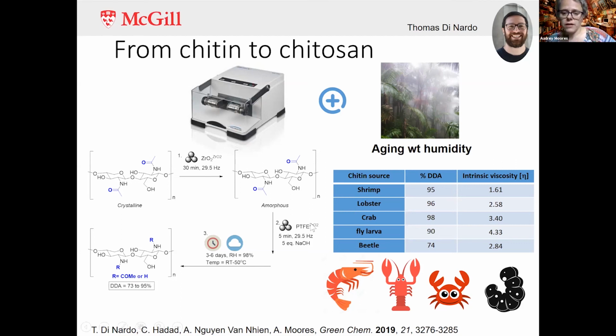Something else that we realize as we do this is that we also make chitosans that have much longer polymeric chains. So we're preserving the structure of the initial chitin much better, and we've made chitosans that have completely new properties. In particular, this chitosan does not dissolve in water or acidic solution, which means that we can start to make stuff with it. We can make a cup, we can make a piece of something that's not going to dissolve in water.